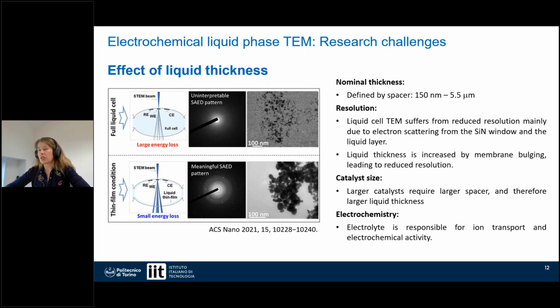And this means that with this reduced liquid thickness and liquid covering the sample, the acquisition of good resolution images is possible, and it is also possible to perform chemical analysis through EELS and structural analysis through selected area diffraction analysis. This is very different from when we are performing the characterization with a big thickness of liquid, where the resolution of the image is very poor, and the chemical or structural characterization is also uninterpretable.